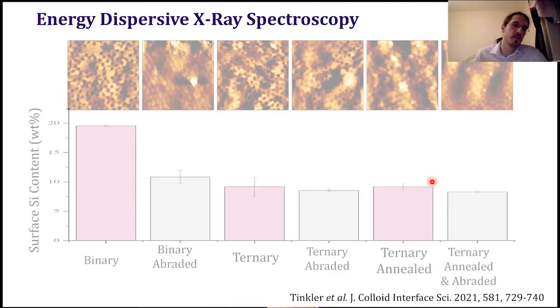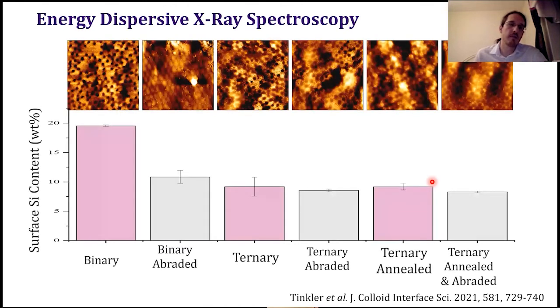So we looked at how much silica is gone after abrading using energy dispersive X-ray spectroscopy. For the binary, after abrading it went from 20% to 10%. So it was reduced by 50%, which is very significant. Whereas in the ternary, looking at the error bars, there was no reduction in the amount of silica at the top, really. And for the annealed ternary blend, we have a very similar result. So this is a very positive result.